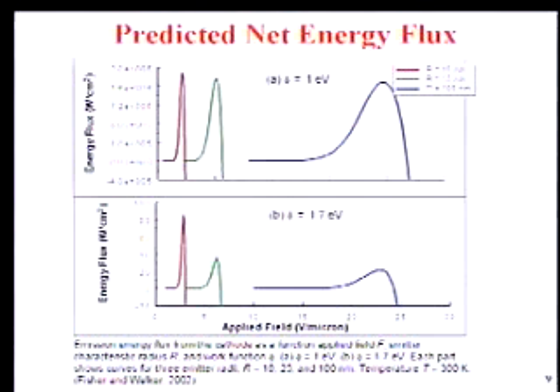If we look at two different work functions, that's the only difference between these graphs. And then a variety of different emitter radii, 10, 25, and 100 nanometers. We actually predict ridiculous energy fluxes, cooling rates from these materials, right? Now, this is a work function of 1 electron volt, and that's itself a stretch because most materials, certainly metals, have work functions that are about 4 times greater than that. But there are some indications that we can get to low work function materials, something more realistic and based on a diamond carbon material. It would be 1.7 electron volts, and even then we get to high energy fluxes.